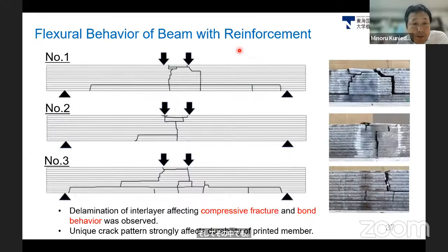So this is just the crack patterns of RC members. As you can see, the flexure cracks occurred initially, and then the number of cracks increased in some cases, and after that, the delamination along the interlayer occurred. And fortunately, in this series, this crack pattern does not significantly affect the load capacity, as you can see in the load displacement relationship.